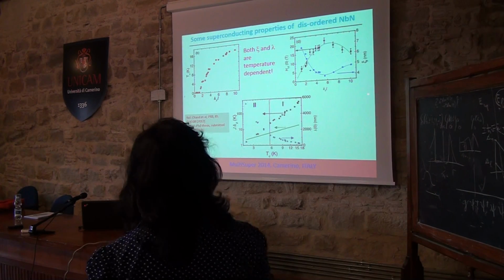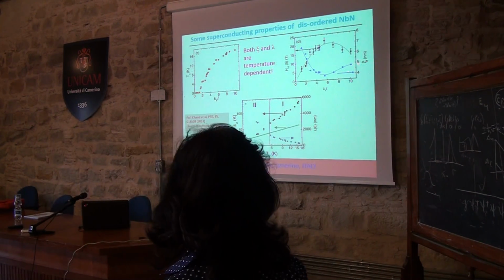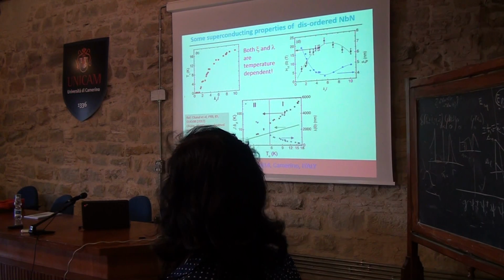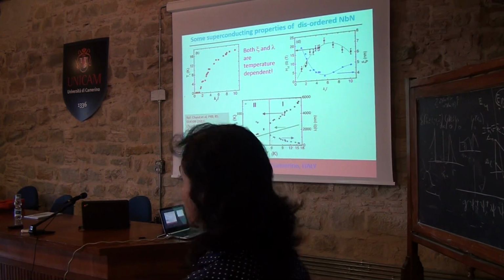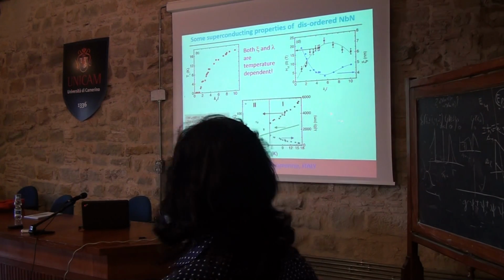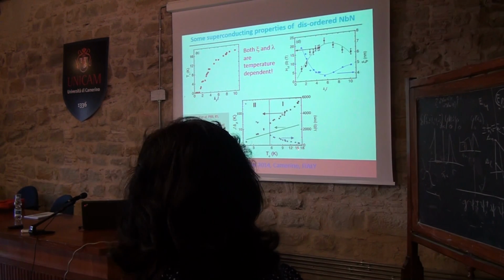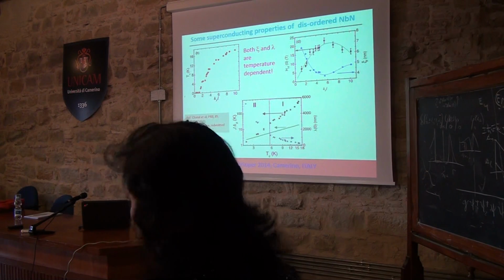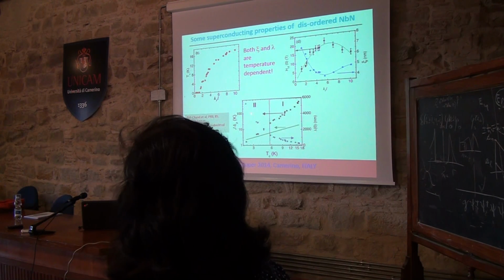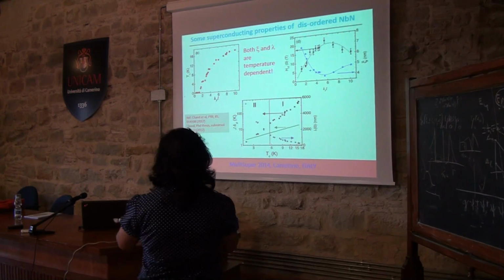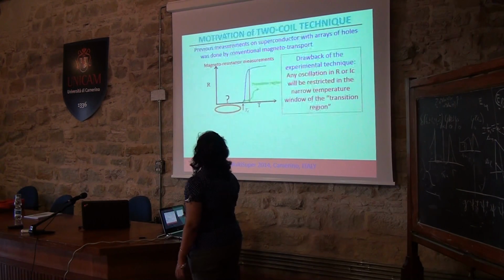Interestingly, if you measure the superconducting parameters as a function of disorder, the coherence length does not change much. If you see this blue line, the coherence length changes from around 5 nanometer, shows a small dip, and then increases to about 7 nanometer. So the coherence length does not change much with increase of disorder or decrease of TC. But interestingly, the penetration depth changes by almost an order of magnitude. If you take the penetration depth of your least disordered film, which has the maximum TC, it is around 200 nanometer, and it shoots up by almost orders of magnitude when you make the films more disordered. So this really will help to tune the intervortex interaction.